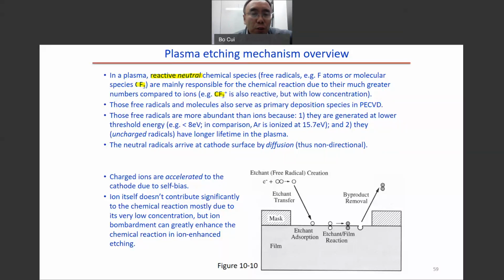So why do we have more free radicals than ions? First, the neutrals are generated at a lower threshold energy, for instance, maybe less than 8 electron volt. For comparison, argon is ionized at 15.7 electron volt. So it's more difficult to form ions than to form free radical neutrals. Secondly, those free radicals are not charged, they are neutral, so they have longer lifetime in the plasma.